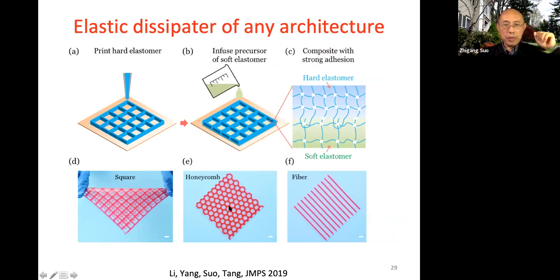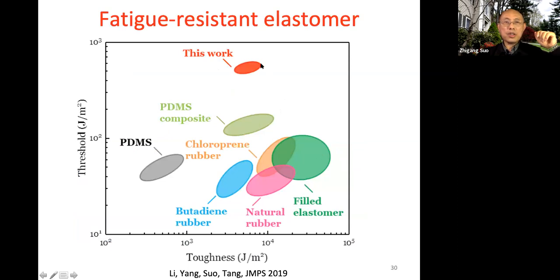So once we do it this way, we have a honeycomb, a square, and a fiber, and these materials, we test them. And this work just has an enormous threshold. This guy is 700 or so, a threshold unheard of before for any rubber. So this is all existing rubber, commercial rubber, including filled rubber or whatever you do, it's just no good in terms of threshold. Natural rubber, the gold standard, not very good in terms of threshold. All right, so